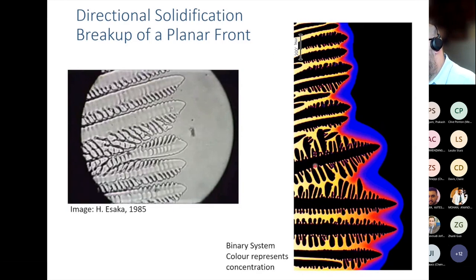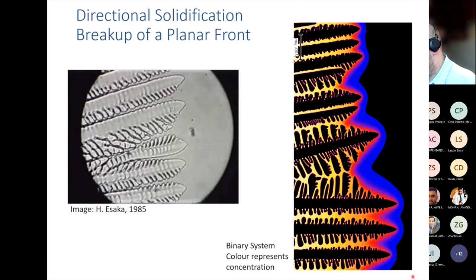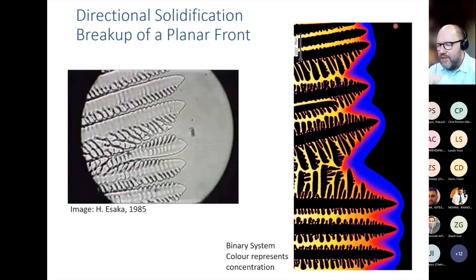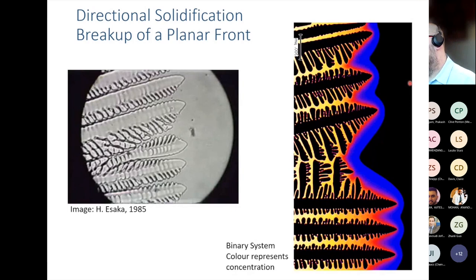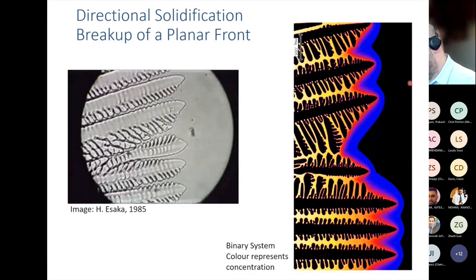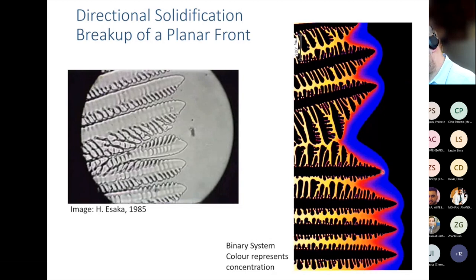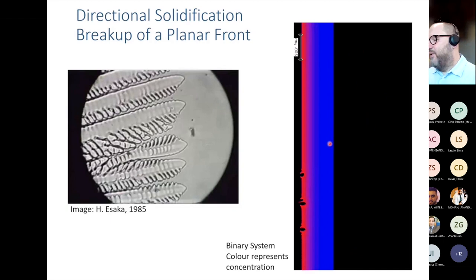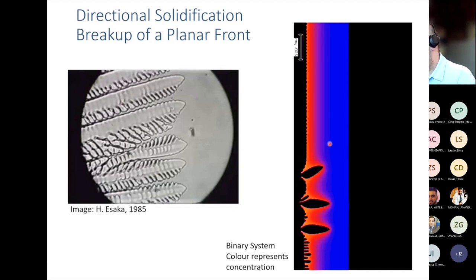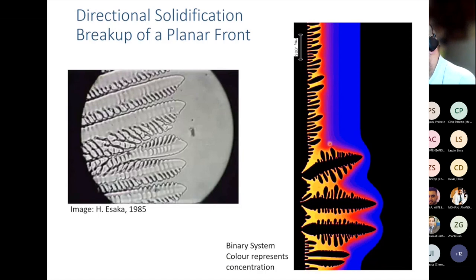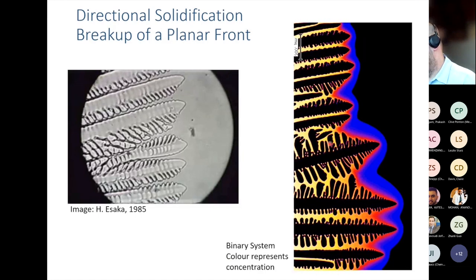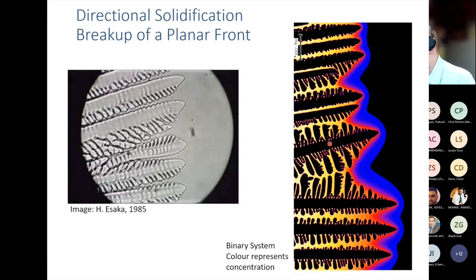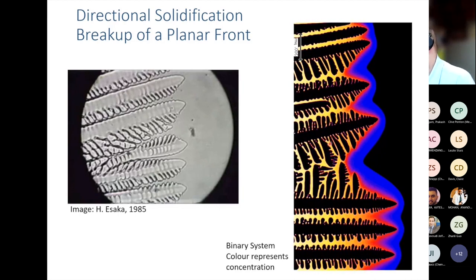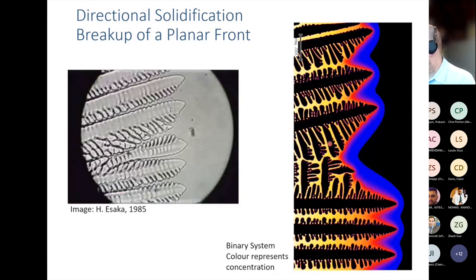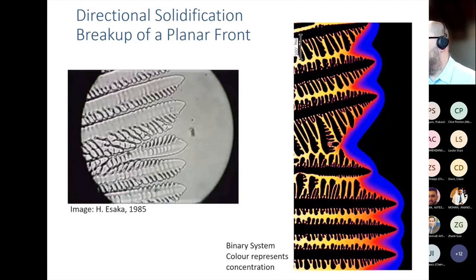Again, the growing crystals are black, and there's a black layer as well, which is ahead of the solidification front, which is liquid that has not been affected by the segregation of elements. So we found the typical patterns, the dendrite tips forming, there's a new primary that has been forming, side arms forming, and all that grain selection that we typically see as well in the experiments using the organic model systems. So we now have a tool that convincingly gives very, very similar patterns, and that allows us to study these patterns and predict some of that, where we could just now do studies on what happens if we change something.